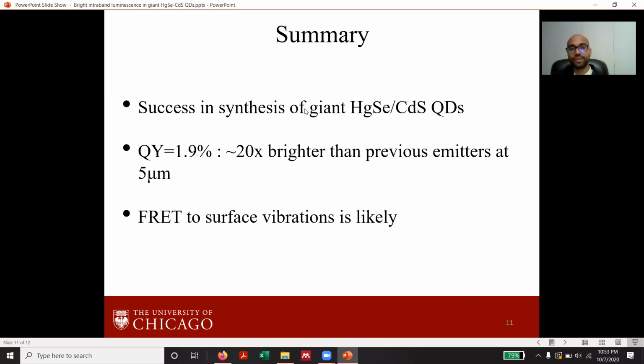In summary, we have discussed today our success in growth of giant mercury selenide CdS quantum dots. They are 20 times brighter than the previously reported dots at 5 microns, and these have a quantum yield of 2%. The trend of the quantum yield versus thickness shows that Förster energy transfer from the quantum dot to vibrations on the surface is likely to be the dominant mechanism.